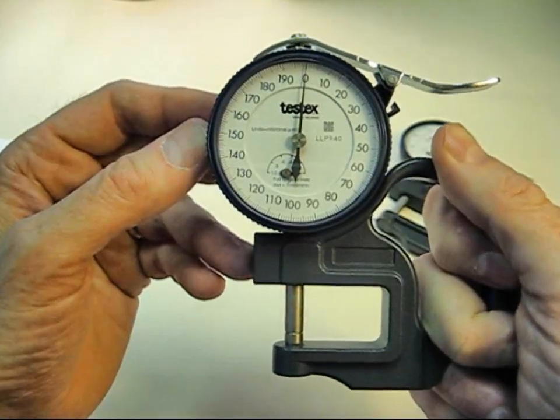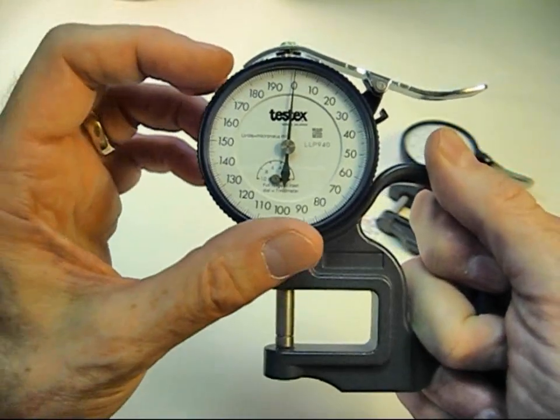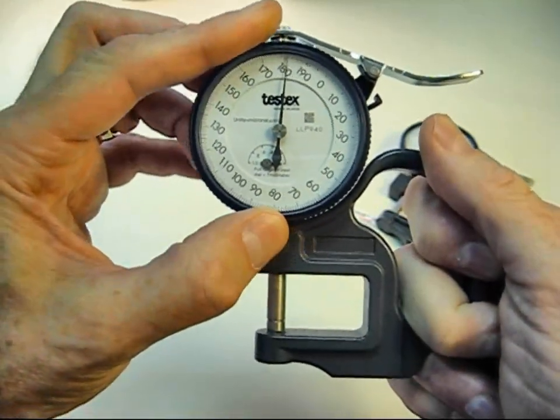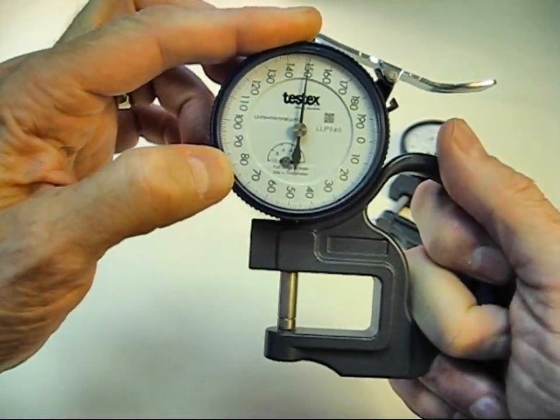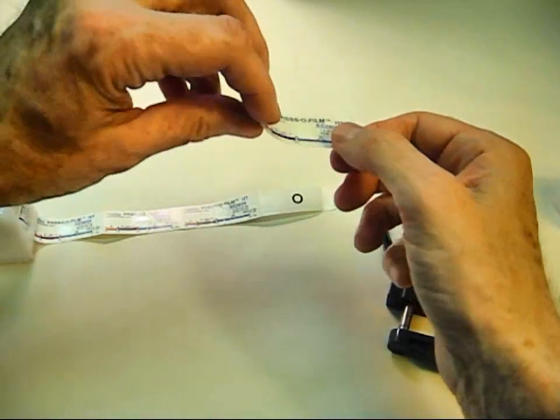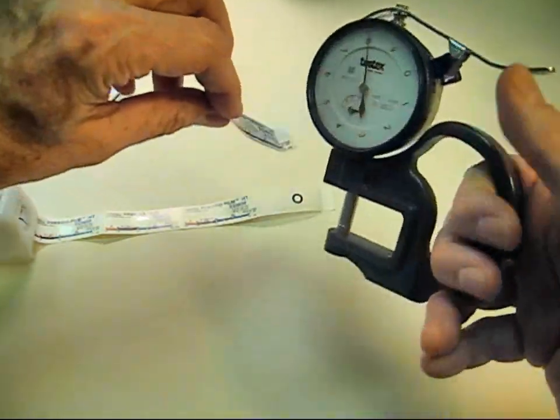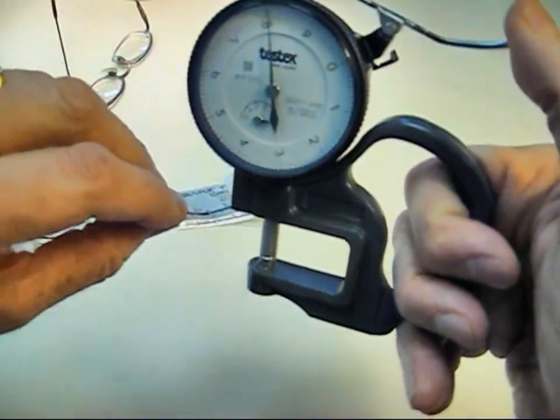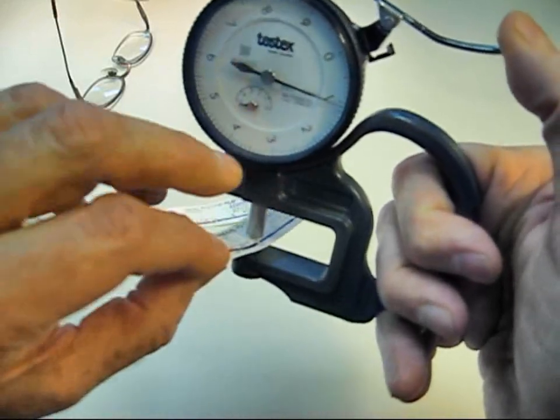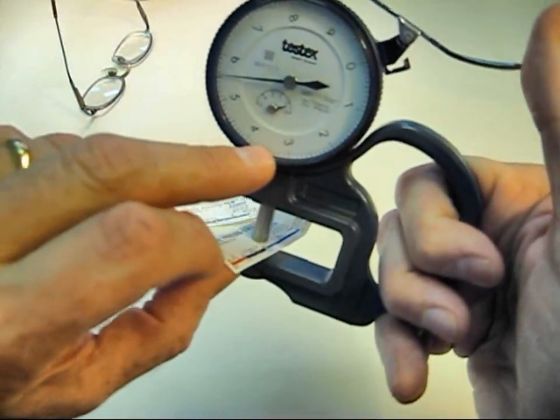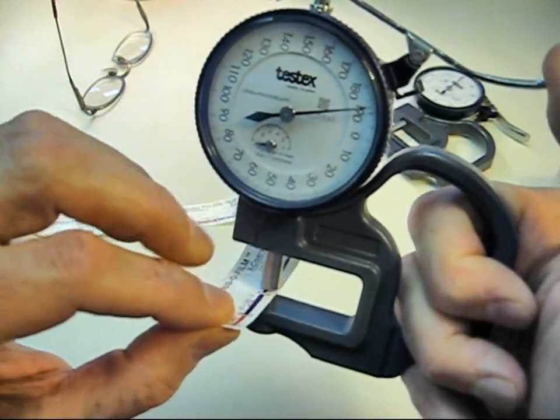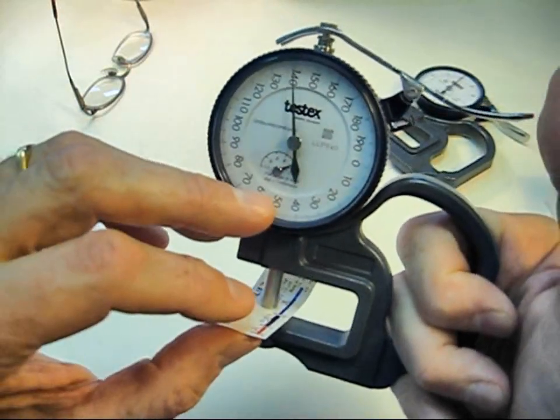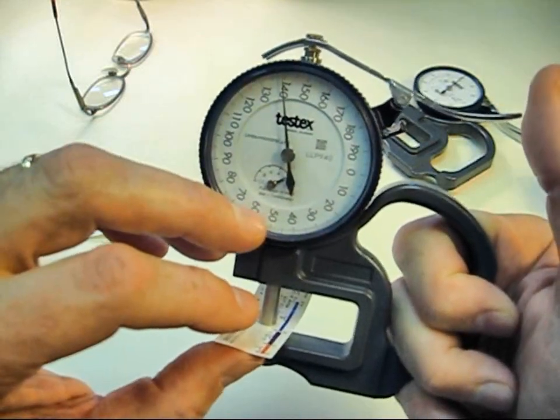On a metric gauge, it means presetting to minus 50 micrometers, or plus 150 micrometers. To make sure everything is working properly, pre-gauge a piece of tape. If you're using X-Coarse grade, you should see a thickness between 5 and 6 mils. If using a metric gauge, the thickness should be between 125 and 155 micrometers.